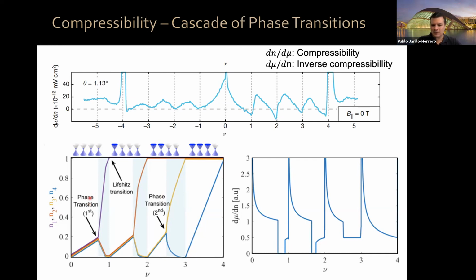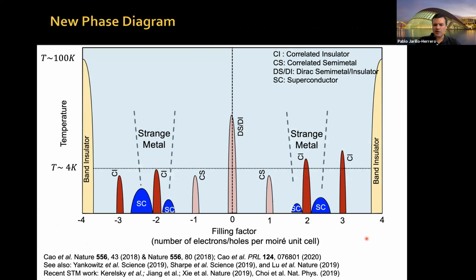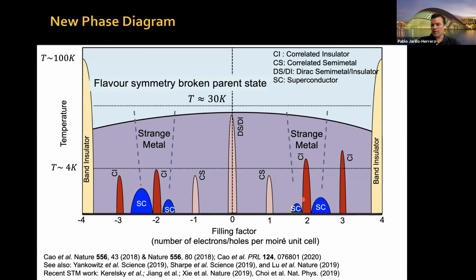So as you can see, there is a cascade of flavor polarizing transitions in your system. In the simplest model, that gives you an inverse compressibility which has a sawtooth type of behavior like this. And again, there are nowadays more sophisticated and more complete models that describe this behavior. Now, this means that in the phase diagram of magic angle graphene, you have all of this correlated insulator behavior, superconducting domes, etc. But there is an overarching flavor symmetry broken parent state on top of which these correlated insulator states and superconductivity develop. And this flavor symmetry breaking, this cascade of phase transitions, I don't have time to show you the temperature dependence, but occurs already at very high temperatures, of the order of 50 Kelvin, 70 Kelvin even. I put here 30 Kelvin very conservatively. We have seen it happening even at 70 Kelvin. So that's something that should be in your minds as you look at magic angle graphene. The system changes at the integers.